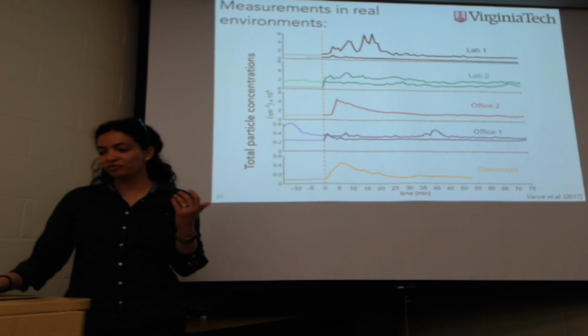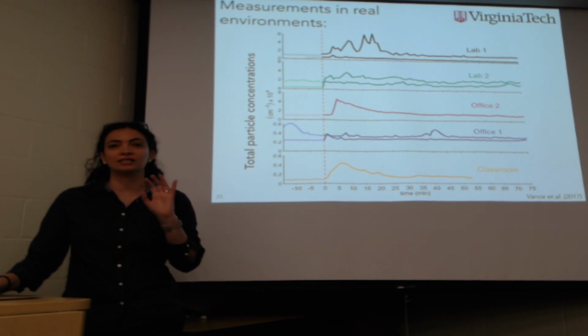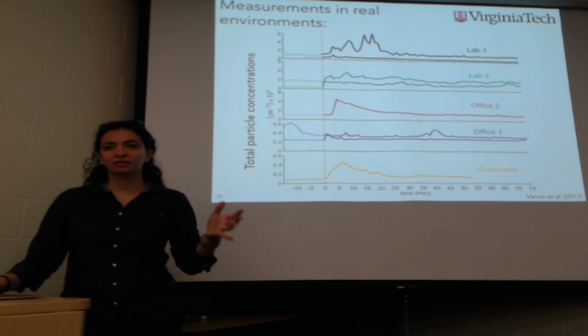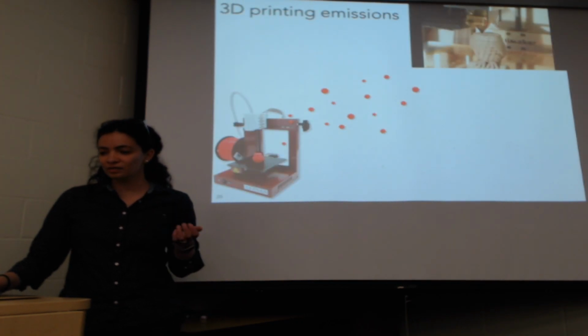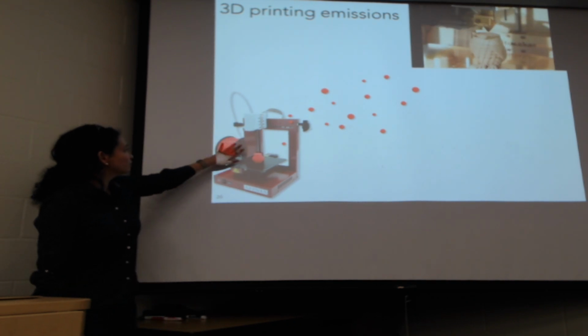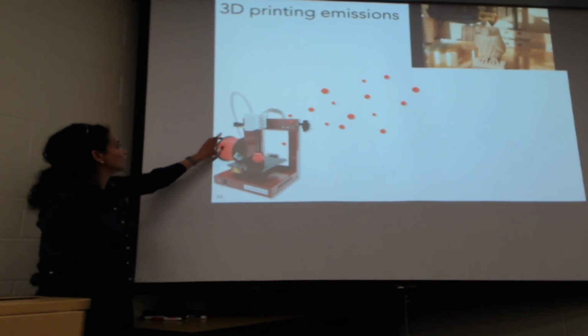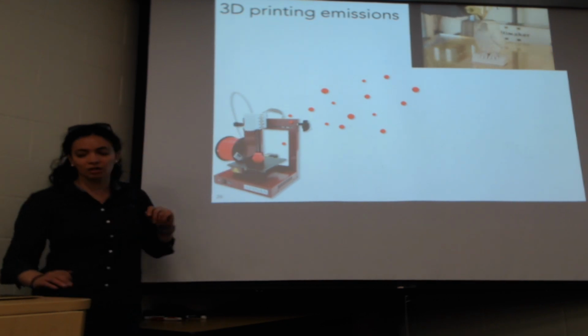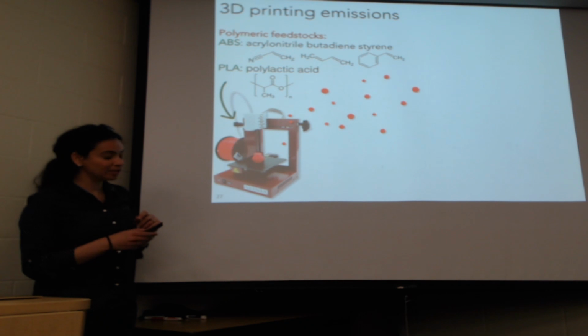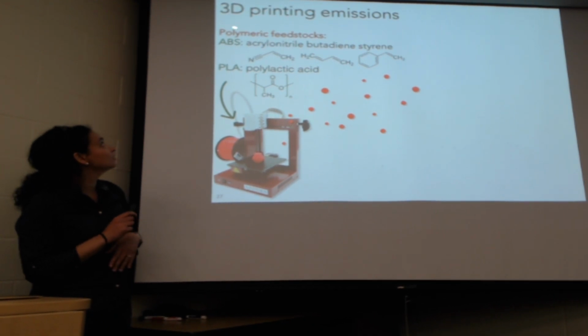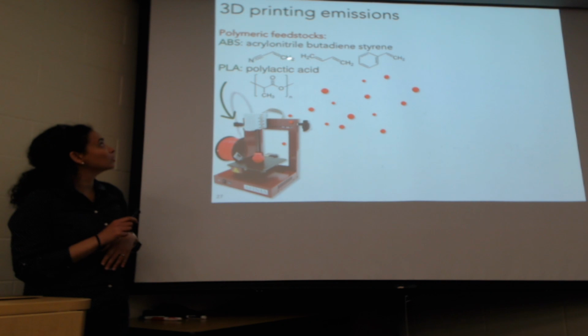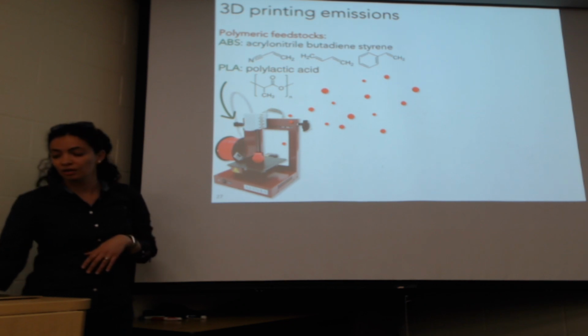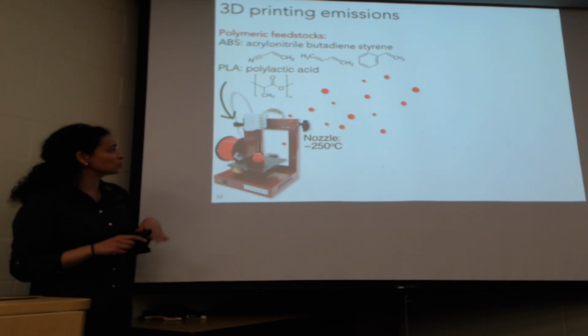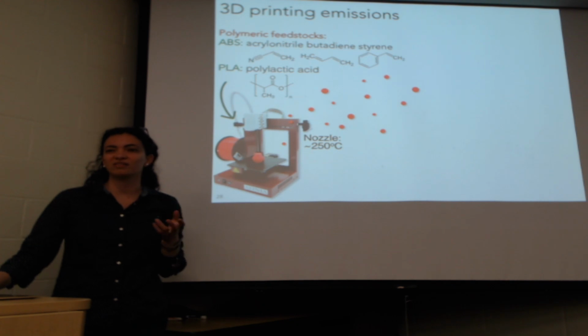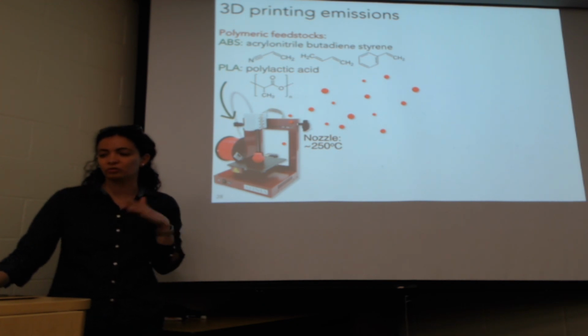So then we decided to follow up with more controlled studies inside a chamber in the lab to really understand the fundamentals of the process. So what happens here is that you have this polymeric filament being extruded through a heated nozzle. The most common feedstocks are PLA, polylactic acid, and ABS. That stands for acrylonitrile butadiene styrene. And here are the monomers that make up these polymers. The temperature of the nozzle is usually around 250 degrees Celsius. That varies a lot from printer to printer and material to material.